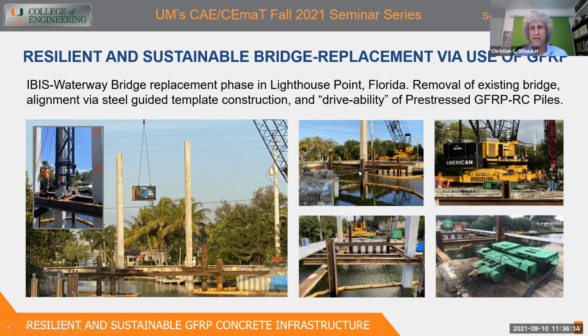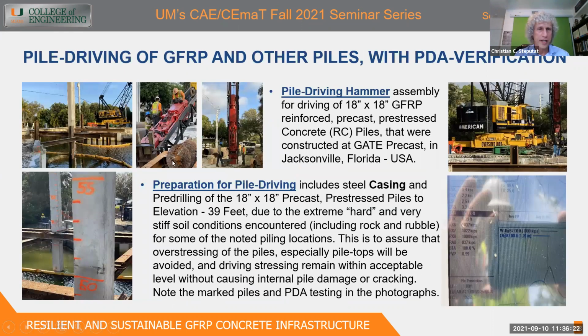Unfortunately, we had a lot of severely differing site conditions. So we had very hard soils and we had very loose soils, which made it very difficult to drive. And you will see that in some of the pictures in a moment for different pile lengths. You can see the hammer in the top middle pictures, the red one. You can see here 55, 50, those are our markings. What is important, we had such dense soils, we would have damaged the piles driving.